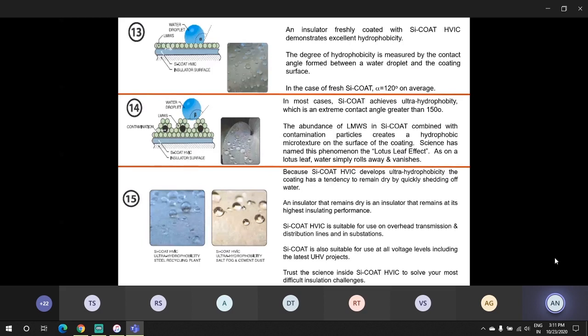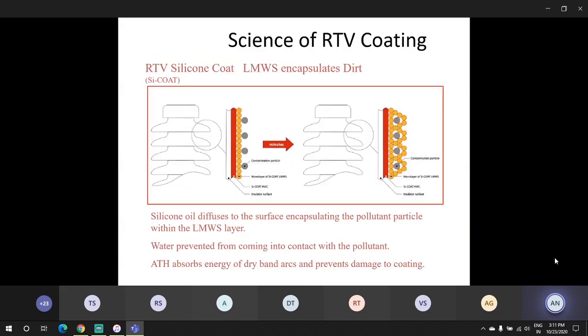So if you see in point number 15, steel recycling plant and cement dust, you can see the water droplets are circular in nature, and it rolls down the surface without sticking to the surface. This prevents any discharge activity on the surface, even though it is a contaminated surface.